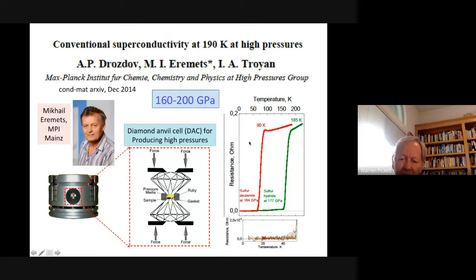And they also measure these curves when a magnetic field is applied down here. That's not so easy. Well, actually, if you make this right, you can just put the whole thing inside a large magnetometer. And as you increase the magnetic field, the critical temperature decreases. And that's an important sign that it is superconductivity that's causing this, and not that, you know, a lead fell off or something like that. This is a tough experiment.